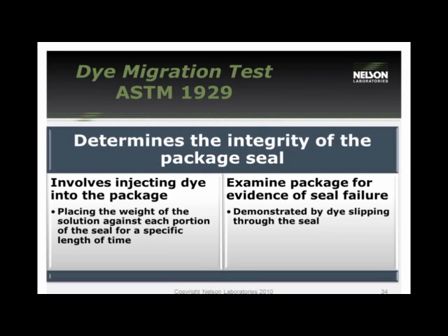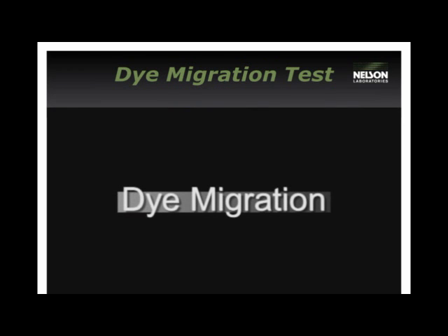The next test in the integrity is dye migration. Dye migration is regulated by F1929. It will help identify the integrity of a package seal specifically. The process involves injecting dye into the package. Then the weight of the solution sits on the seal. We do it for a specific length of time. And then you're looking for evidence of the dye slipping through the seal.